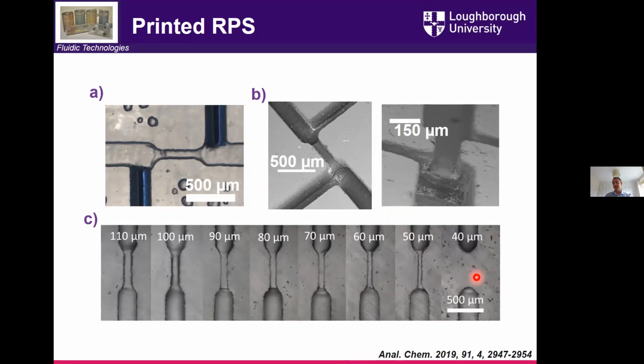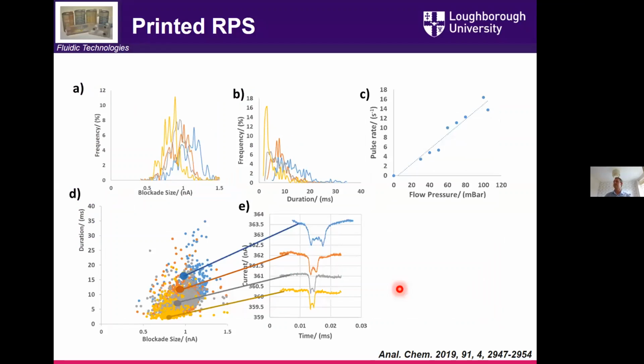And when it comes to counting droplets and nanoparticles, size is key, because in resistive pulse sensing experiments, your channel, your sensing zone here, has to be about an order of magnitude within the material that you wish to characterize. And so if you're printing something about 50 microns in size, you might be able to characterize 5 micron droplets, but nothing of any smaller. And so the idea is to try and get it as small as you can. But for now, in this process, we were stuck at 50 microns.